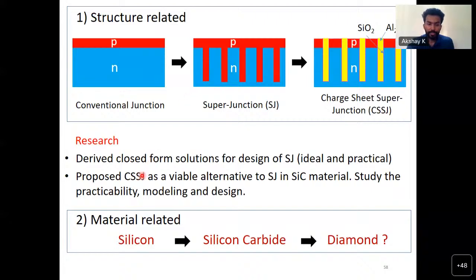So we took this up as a problem, and the way we could propose at least a theoretical solution is a new device structure wherein we suggested replacing the P pillars with a bilayer of silicon dioxide and Al2O3. What this combination does is that along the interface, along the trench wall, you will have a negative interface charge. And that interface charge magnitude can be controlled by the deposition temperature. The function of the P pillar was just to eat up the N pillar charge, right? As I explained to you before, the function of the P pillar is just to eat up the N pillar charge. So if you provide the equivalent amount of P pillar charge using this interface charge, then the requirement is satisfied here also electrically.